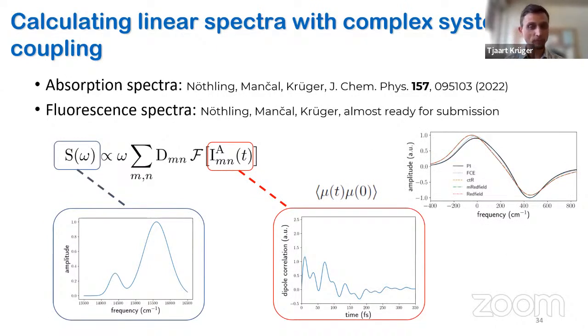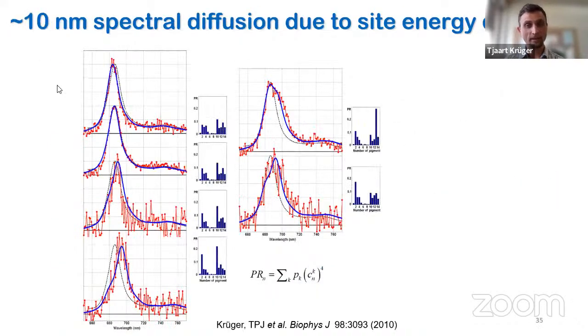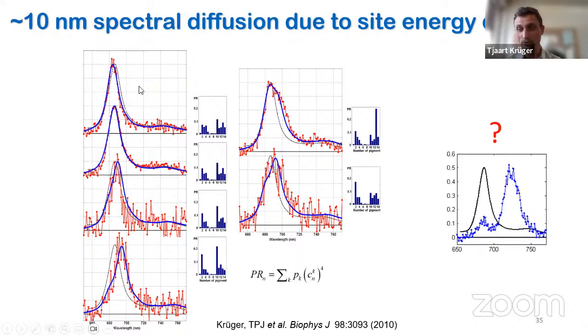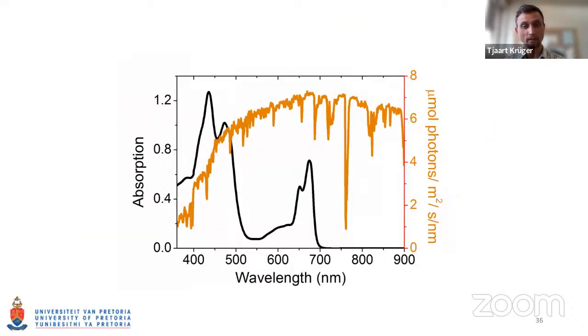Okay, so this is what was applied in this case in order to explain spectral diffusion within 10 nanometers by means of energetic disorder, site energy disorder. But what about a shift like this, which is much larger than 10 nanometers? This prompted us to look at a different photosynthetic system.